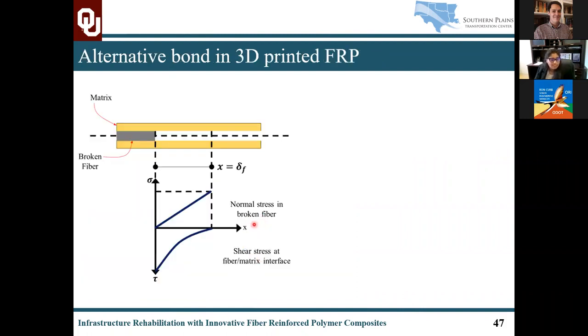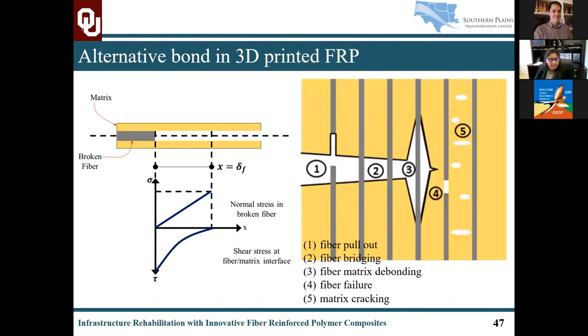Other improvements that we see in the near future are alternative bonds in 3D printed FRP. Bond between layers is a very, very crucial aspect in how the failure happens. So there are different kinds of failure and damage parameters in the overall failure of the composite. If we consider these as the different layers of FRP, and the yellow color represents the matrix itself, there's fiber pullout, there's fiber bridging, there's fiber matrix debonding, and fiber failure and matrix cracking that happens in FRP.